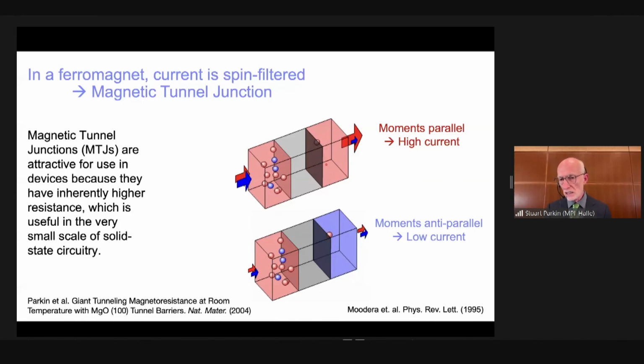So the electrons that are tunneling are automatically spin polarized, but they have defined states on the opposite side of the tunneling barrier which have the same spin polarization. This is only possible when the magnetic moments are parallel to one another. When the magnetic moment on the right-hand side is reversed, becoming blue, then the electrons tunneling of the red characteristic find only blue states to tunnel into, and that's not possible. The electron spin is conserved in this tunneling process. This leads to a dramatic increase in resistance in the lower configuration. And indeed, the change in resistance for this type of tunnel junction can be several 100% at room temperature.